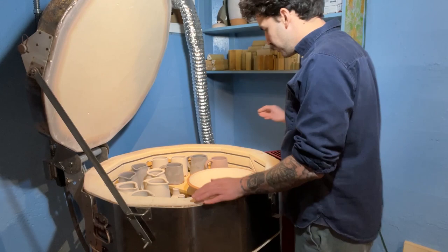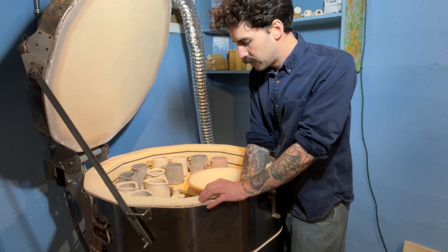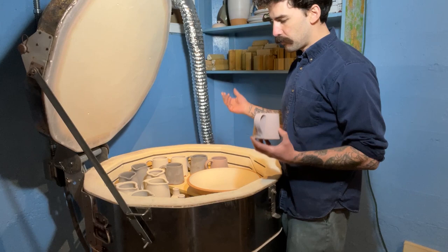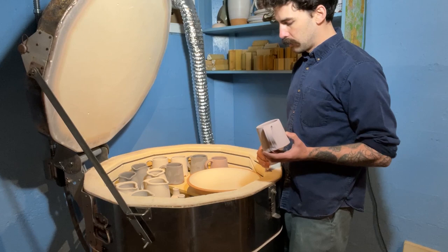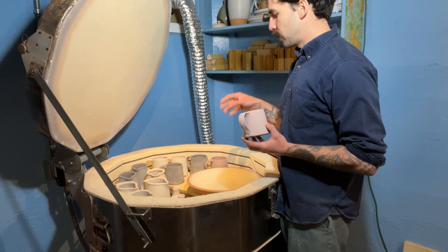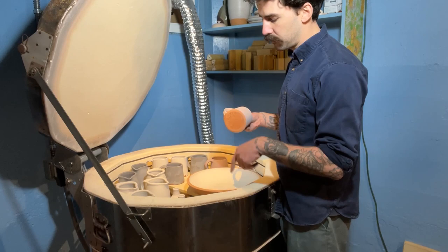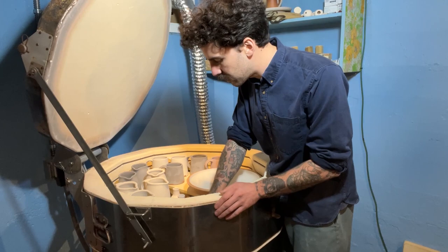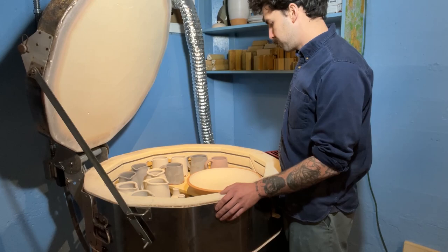I have just maybe three or four of these raw glazed mugs at a different part of the kiln. Heat rises, so generally the bottom of the kiln is the coolest part. Some of my glazes and clays like to fire on the cooler side, whereas some like to fire on the hotter side. So I placed some in the middle and a couple on the bottom as well. The middle where my thermocouple is is generally the hottest part, and it'll be interesting just to see the results of what these pieces prefer.